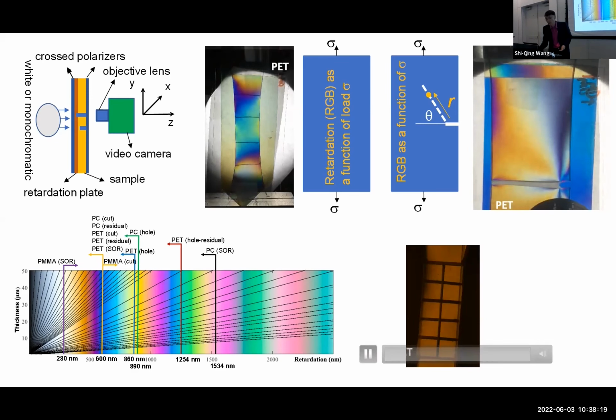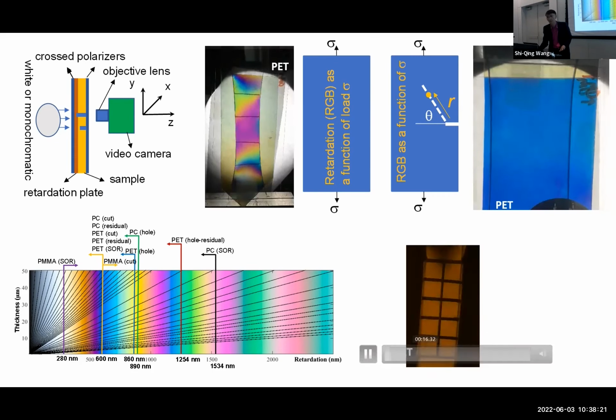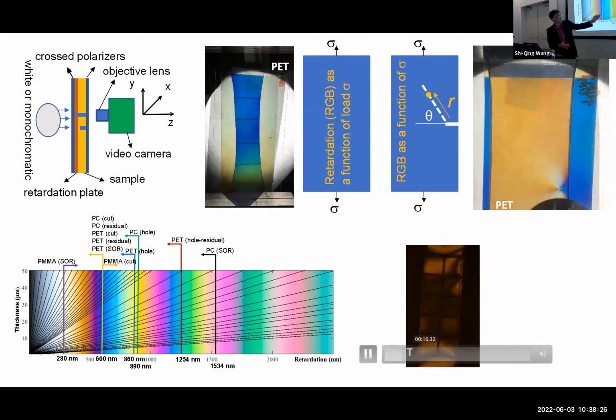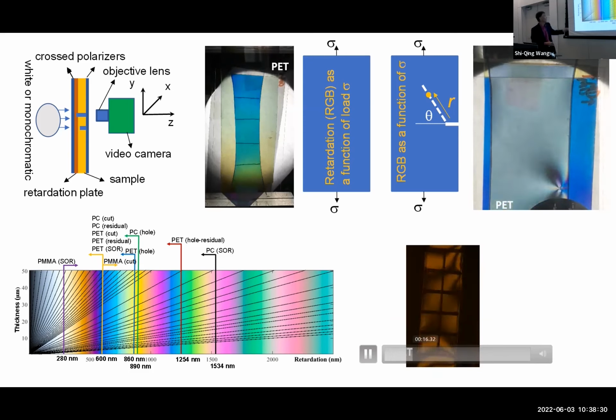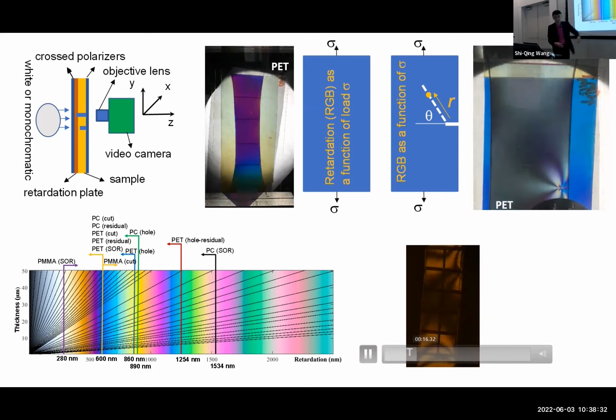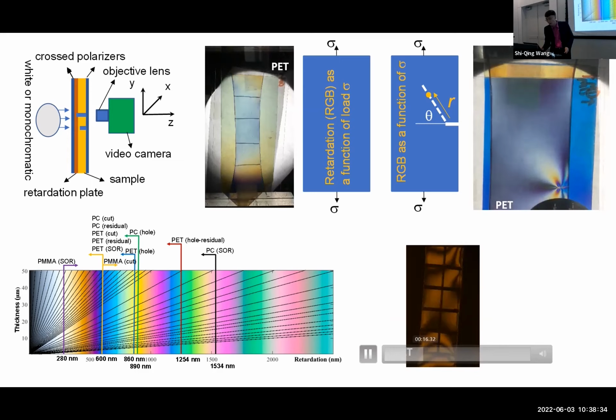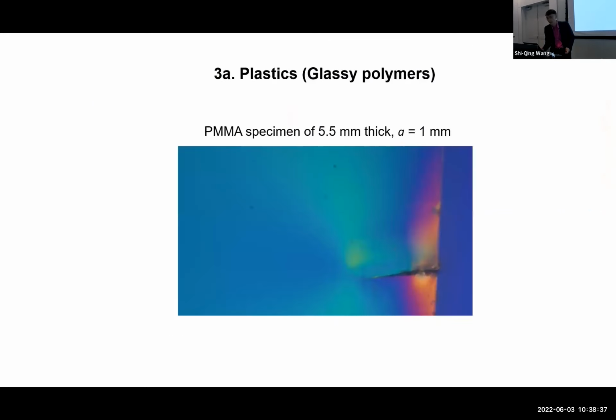And better yet, if you have very birefringent materials, you don't use white light, you use monochromatic light and just count the number of fringes as it turns black and white, black and white. For white light, you have this Michel-Levy chart to guide you about how the birefringence builds up. So here's our first result: PMMA with a cut, with white light. As the color changes, it shows the birefringence progresses.